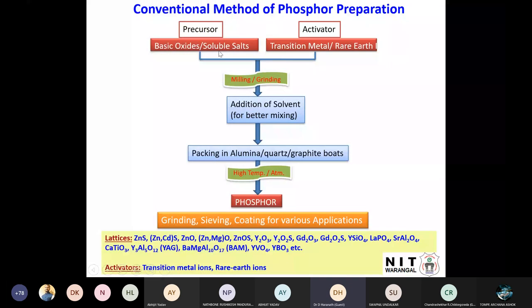And this is a simple conventional method of preparation, the solid state reaction. You take powders of oxides and activator powder, mill it, grind it in a pestle and mortar. And if you want to mix it very well, you can add a little bit of solvent like alcohol or a little bit of acetone. You can put it in and mix. This is only for better mixing. No need for the solvent. Dry mixing you can also do.